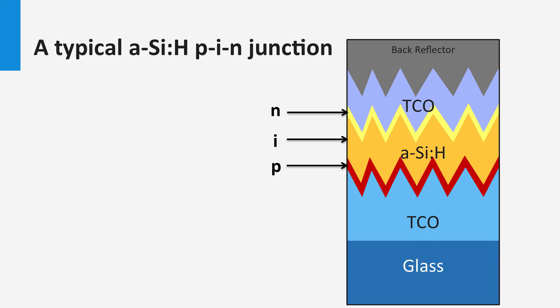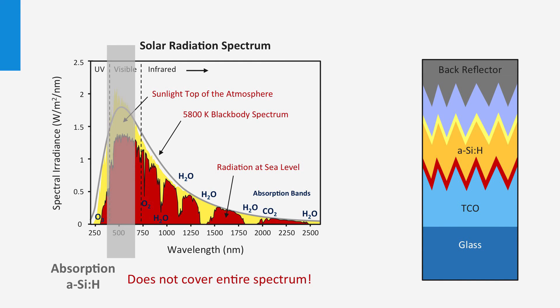As the bandgap of hydrogenated amorphous silicon is relatively high at around 1.75 eV, it only has a spectral response below wavelengths of 700 nm. The best current densities in single junction amorphous silicon solar cells are 17 to 18 mA/cm², against a theoretical maximum of ~23 mA/cm², giving a spectrally averaged EQE of about 74 to 77%. The best open-circuit voltages are around 1 V. The best stabilized efficiency of a single junction cell is 10.1%, obtained by the research lab of Oerlikon Solar, currently part of Tokyo Electron.